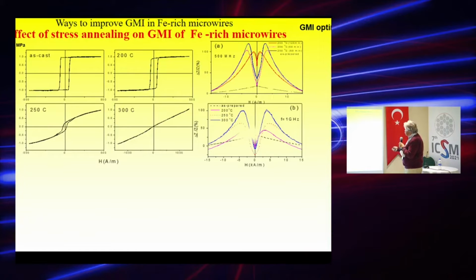And changing the composition and the conditions of thermal treatment, we can also tune the magnetic field dependence. This is at a fixed frequency, 500 megahertz, and you can see the curves are different for different kinds of annealing. This is the same, in fact, as the hysteresis loop. So the largest field of maximum corresponds to the largest magnetic anisotropy field.